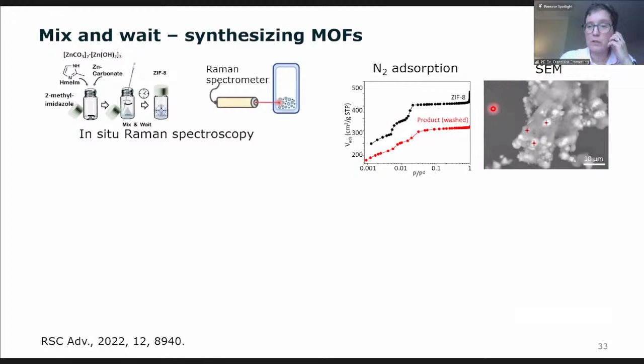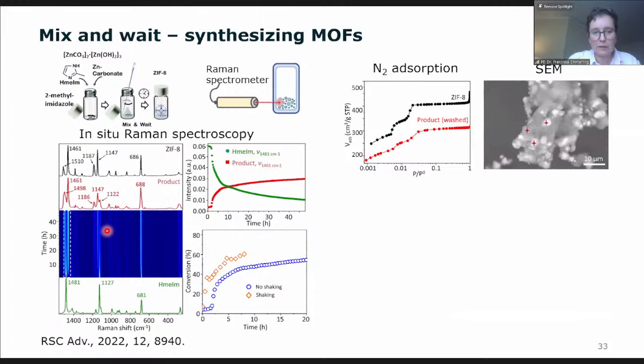Before, of course, we checked our material ex situ. You can see here ZIF-8, that's a commercial material, and that's our product. Not so super in this case when it comes to adsorption, but also doing fine. And here are the SEM data. I'll come to those in a bit. And then we looked at the Raman spectra, and you can see here, these are spectra taken every 15 minutes. So we took a Raman spectrum, and you can see here how the product is formed here in the red line. And it is clear, we don't get a full conversion, but somehow we end up with an okay amount